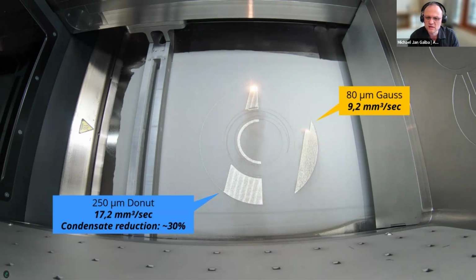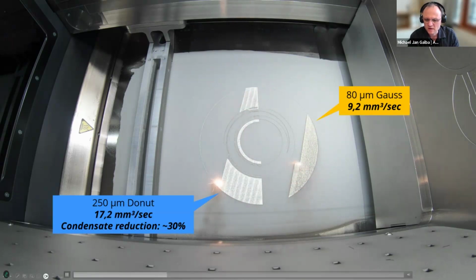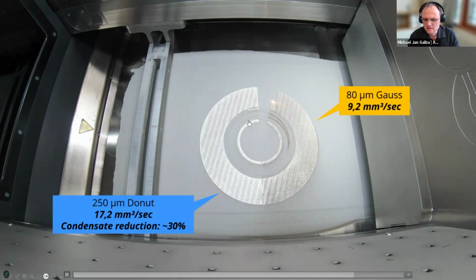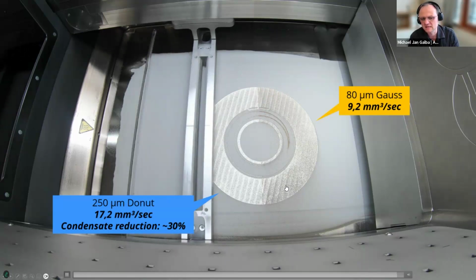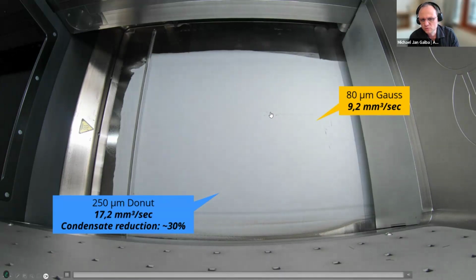So when I initially showed that there are fewer process spatters and fewer process side products being emitted, here you can see that after a while, I will just forward the video, the Gauss beam is still operational, whilst the nLIGHT AFX laser is already done with all the melting. Just look at the top surface of the melt. It's completely clean. There's no debris, there's no spatter in the powder bed. There are no overmolten particles being deposited that can alter your product quality. Also, recoating is a lot smoother in the beam shape process.